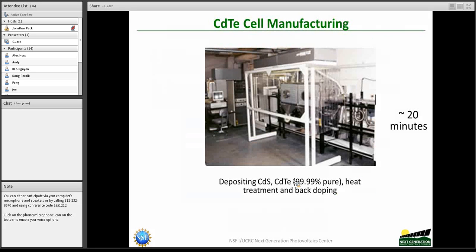Now the machinery to produce the cadmium sulfide coating, the cadmium telluride coating, and a bit of heat treatment and doping of the back is shown here. This was an old system we had in the lab that would fabricate 3-inch by 3-inch solar cells. This machine, about 6 feet long, would do the cadmium sulfide, the cadmium telluride, the heat treatment, and back doping. And the whole process took about 20 minutes from front to back to complete. And you can see the schematic of this process in the next slide here,